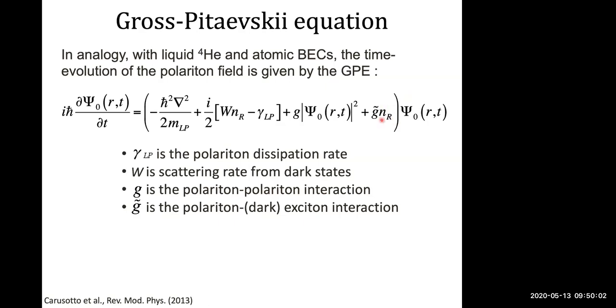n R is the number of dark state excitons, so the reservoir density. G tilde is the interaction strength between our polaritons and this dark exciton reservoir. And here, the pump term is given here. W is the scattering rate from the reservoir to the condensate. And gamma LP is simply the condensate or lower polariton lifetime.